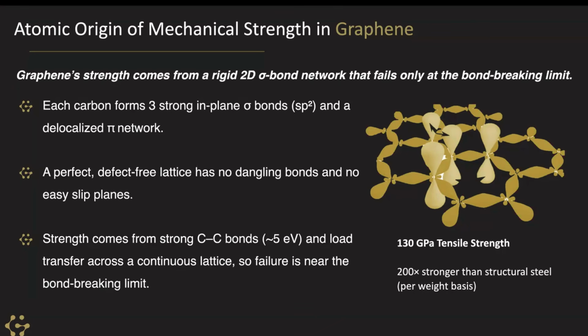So when you pull graphene, you're stretching the carbon-carbon bonds directly. Now, failure only happens when those bonds break. So that's why the tensile strength reaches around 130 gigapascal, which is roughly 200 times stronger than structural steel on a weight basis.